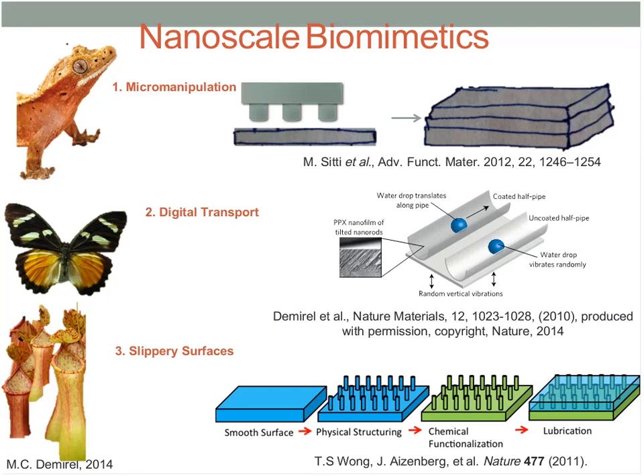During release of the part onto a receiver substrate, the contact area of the pillar to the part is drastically reduced by controlled vertical or shear displacement, which results in reduced adhesive forces. They also claim that the compliant polymer micropillars are safe to use with fragile parts and could be effective on most materials and in air, vacuum, and liquid environments. This work was published in Advanced Materials recently.